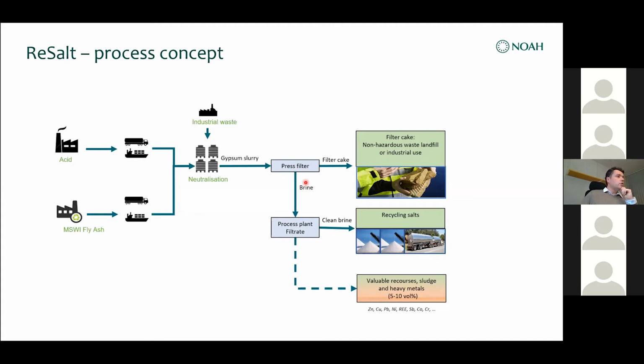The other stream out of the press filter is brine, obviously, and this brine will go into a process plant where we have to clean it before it goes into a recycling plant. The main challenge is sulfate, because we don't want sulfate to co-precipitate with the other salts. The metal content is very, very low because this process is very robust. So the clean brine will go into a recycling plant to recycle the chloride salts. The sludge here can either be recovered or go into a landfill.